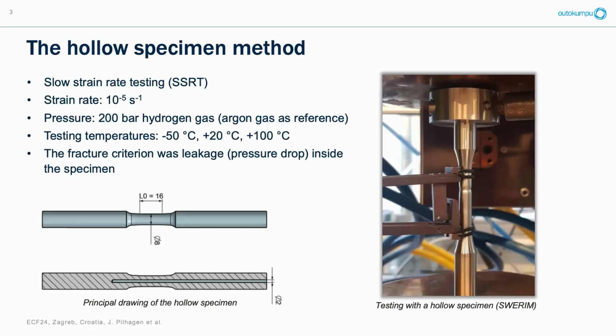And typically when you measure the hydrogen embrittlement, you use the area reduction or the fracture elongation. But we saw that in these kind of hollow specimens, you typically get a pressure drop. That's because the fracture does not happen on the entire specimen at once, but you get surface cracks before, and then you lose the pressure. So we decided to define it as the elongation to the pressure drop.